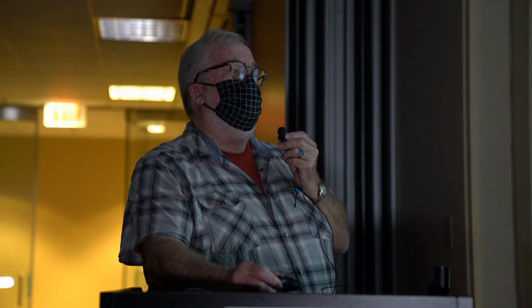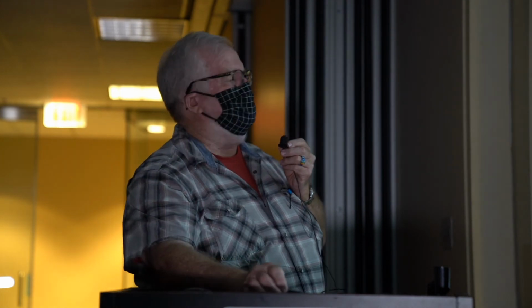So that's the status of the GMT at the moment. We're the third mirror, we finished 2 of them. The third mirror, we're down to like 40 to 50 nanometers RMS. We need to make a factor of 2 improvement, and we're having some issues seeing the whole mirror and getting the edges done. If you wanted an 8-meter mirror, we could have finished it 8 months ago, literally. But it's the outside 4 to 8 inches, that's just so tough.